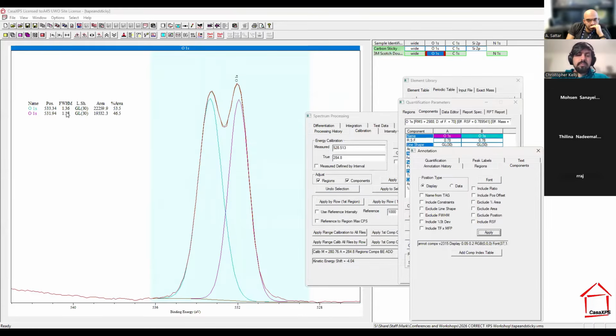And we've got a couple of peaks with a certain amount of area, and we can go in and look at the tables and say, okay, well, this is a certain type of organic oxygen. This is another type of organic oxygen. Obviously, we have 2 very distinct species here on this surface. So that's just a quick run through some very simple curve fitting of these sorts of things. It gets more complicated.